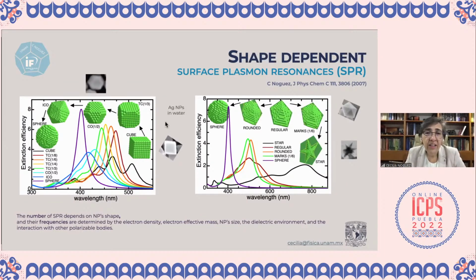When we, for example, truncate the nanoparticle, which are very commonly synthesized in an experiment, for example, I am showing here a micrograph of this kind of nanoparticle, these resonances will change just because of this arrangement of the charges on the surface of the nanoparticle. Okay, so for each kind of nanoparticle, we can have a kind of signature by looking, for example, at how much of the light that is inside the system is detected after you go through a sample of nanoparticles with the same shape in the system.